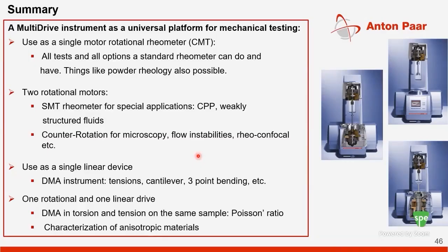I tried to cover a lot today, but you can think of all different types of characterization. We can do dynamic characterization, quasi-static characterization—those are the ring shear cells I talked about. I didn't have time to talk about dynamic testing, an entire slew of experimentation where you can understand the effect of dynamic conditions on powder flowability. This really happens in real life when you're trying to convey a powder, or it's getting moved from a conveyor to a hopper, or there are several touch points. So understanding both quasi-static and dynamic conditions is possible, and on top of that we can understand the effect of extrinsic factors like temperature and humidity. I've worked on interesting projects where things like sticky point can be determined using the humidity setup, so we can understand at what point the powder becomes really sticky. We can do these types of experiments on this device because it's a full-fledged powder rheometer also.